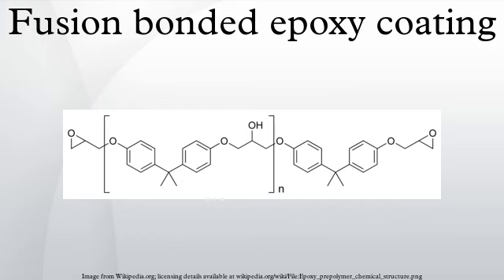Standard coating thickness range of standalone FBE coatings is between 250 to 500 micrometers, even though lower or higher thickness ranges might be specified, depending on service conditions. The molten powder flows into the profile and bonds with the steel. The molten powder will become a solid coating when the gel time is over, which usually occurs within a few seconds after coating application.